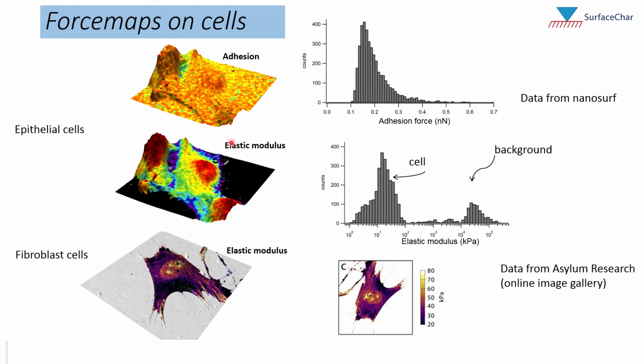Here is a force map overlaid onto the topography with the adhesion measurement and the elastic modulus measurement for epithelial cells. You can see here a histogram where you can quantify the adhesion and the modulus for this particular sample. For the modulus, this is the modulus of the cell. This is just a background material, so less interesting. And here is another very pretty example of the map of an elastic modulus of a fibroblast cell, showing again the modulus painted onto the topography. We can see that the moduli being measured here are in general very soft, in the kilopascal regime, aligned with what one would expect for such materials.